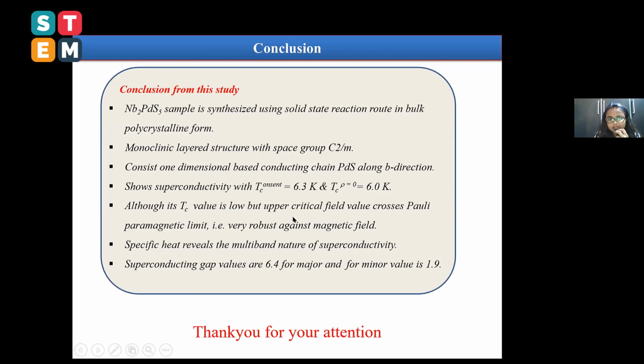And the conclusion is this Nb2PdS5 sample is synthesized using the solid state reaction route in bulk polycrystalline form. The structure is a layered structure with space group C2/m, and it consists of one-dimensional PdS chains along the b direction. The Nb2PdS5 sample showed superconductivity with onset 6.3 Kelvin and offset 6 Kelvin. Although the TC is low, the upper critical field crosses the Pauli paramagnetic limit, which is very robust against magnetic field. And the specific heat reveals the multiband nature of superconductivity. In this case, the superconducting gap values found for the Nb2PdS5 compound are 6.4 and 1.9 respectively. Thank you for